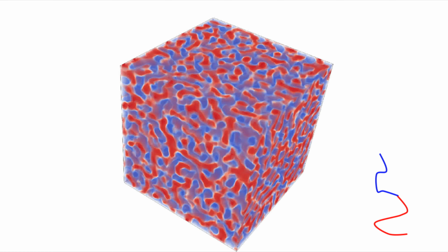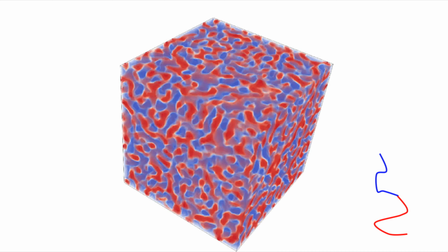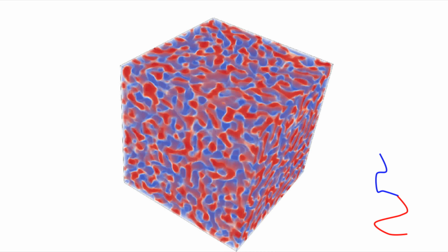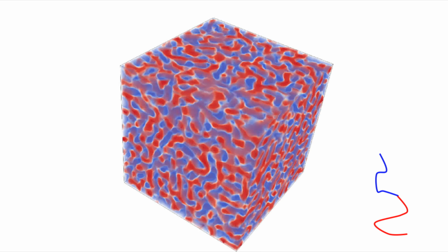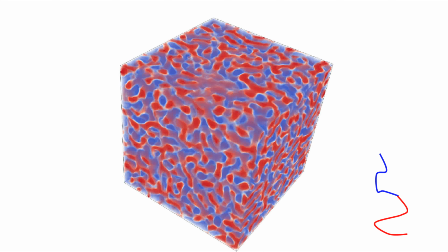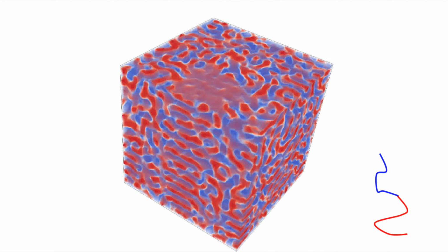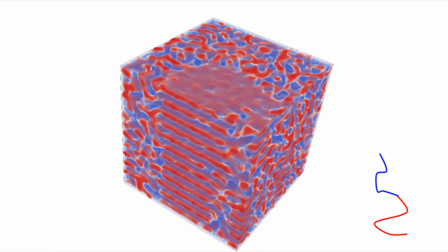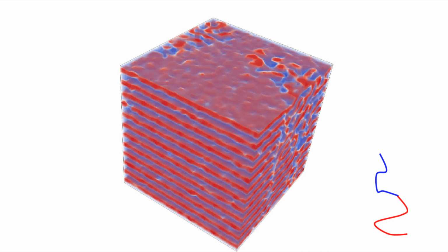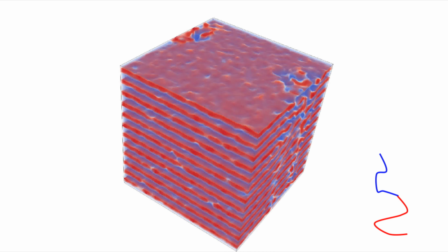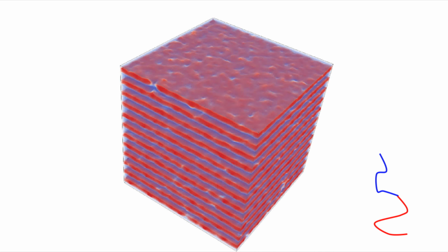This is a Langevin dynamics field-theoretic simulation comparable to the particle-based layer-forming one that I showed earlier, except that the system is clearly much larger, and I didn't have to crank up the interaction strength to get it to actually form layers in a reasonable time. I chose parameters that are close to the order-disorder transition. As before, it phase separates quite quickly into A and B domains, but they form an interpenetrating lattice, not layers. After a little while, some layers start to nucleate and they grow to engulf the system. Soon, all we have is fluctuating layers.